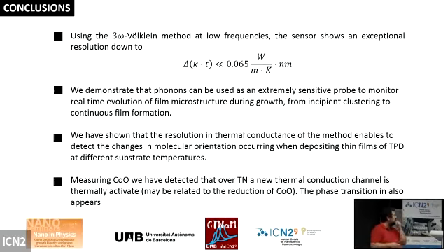But we have demonstrated that phonons can be used as a sensitive probe to monitor the real-time evolution of a film's microstructure during growth, from the incipient clustering to the continuous film formation. We have shown also that the resolution in the thermal conductance of the method enables us to detect changes in molecular orientation, as we have shown for TPD.